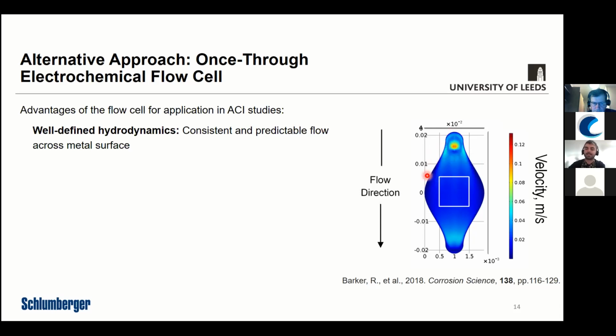And the eye-shaped design is good because it's got smooth edges and it channels the flow. It widens over the coupon, which we've represented by this box here, so that you get a consistent flow pattern across the sample. The color scheme here represents the velocity of the fluid at each of these points within the cell. And as you can see, it's a fairly consistent blue color across the sample, which means we've essentially got a very consistent flow pattern across the sample. That's important because you don't want any variation at different points within the regions of that sample.